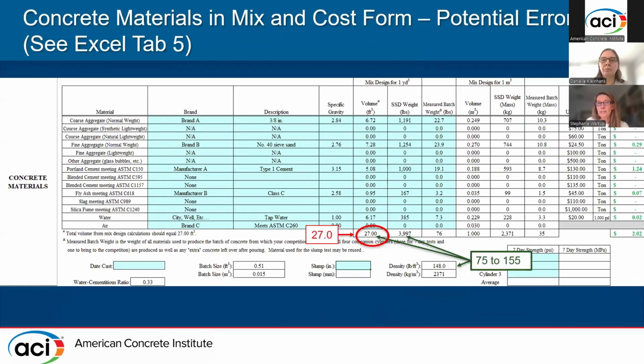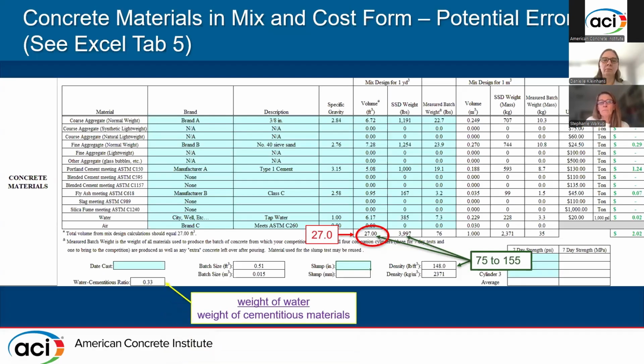The spreadsheet, again, is set up with pre-programmed cells to calculate density based on the saturated surface dry weights and volume that you enter. If this density is not between 75 and 155 pounds per cubic foot, you will receive an error in your spreadsheet, and that's explained in tab 5.